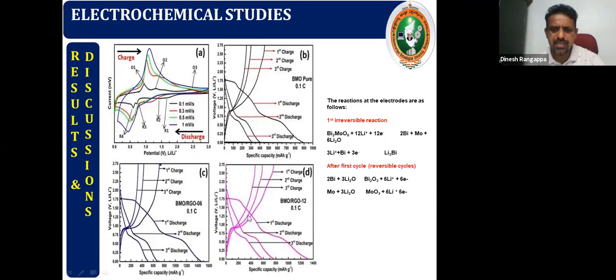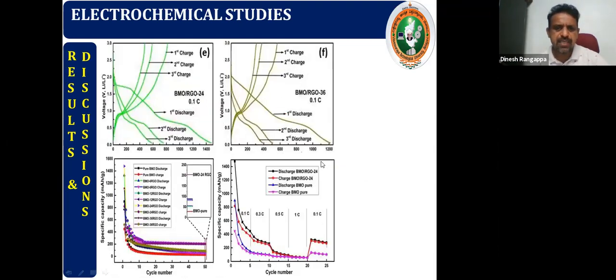So, you can see here the charge-discharge reaction. Compared to the hydrothermal sample, the bismuth molybdate sample from the supercritical fluid process shows enhanced capacity, up to 1400. Pure bismuth oxide shows only 900, and finally stabilizes after the second cycle at about 300. But the bismuth oxide and RGO composite shows increased capacity, especially the nanocomposite with RGO at 12%. You can see up to 600 capacity, 2 times the capacity compared to pure bismuth oxide.